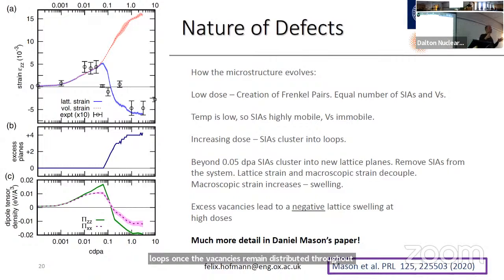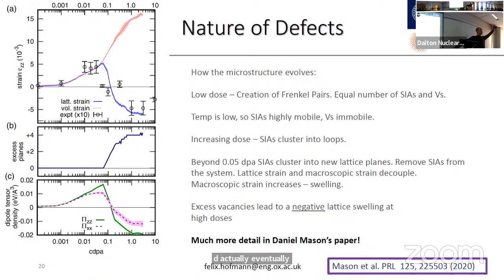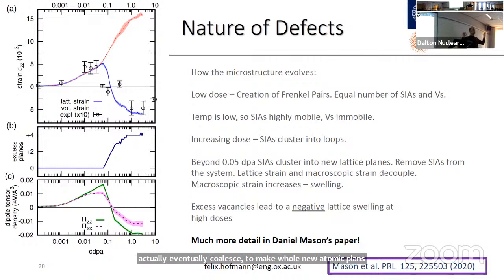These interstitial loops then start to organize and actually eventually coalesce to make whole new atomic planes. So the really cool thing is that those new atomic planes now provide a mechanism for actually pulling all of those interstitials out of your lattice, right? And you can see that. So here, Daniel's plotted the excess planes that are formed.